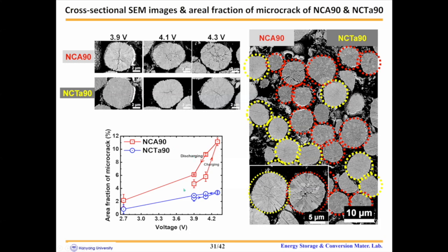And moreover, the areal fraction of the micro cracks in the NCA cathode during the discharge is larger than that during the charging at the same voltage, suggesting that micro cracks do not close completely reversibly. However, the NCTA cathode demonstrates reversible micro crack opening and closing behaviors.